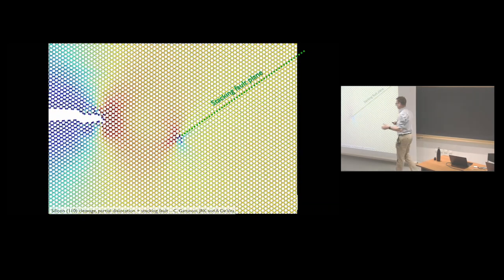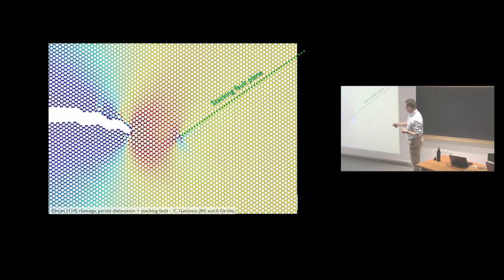This is an example I wanted to show because it was done by a colleague who was at King's together with Giorgia and I a long time ago, Chiara Gattinoni, showing interaction between more than one defect. So now we have a crack here and a dislocation, both treated with higher precision. And we see when we start the simulation, it's predictive in the sense that we don't tell anything what to do. We don't tell the crack where to go. So it's pulled down by elastic attraction towards the core of the dislocation. It's going to take a little wobble and come down.